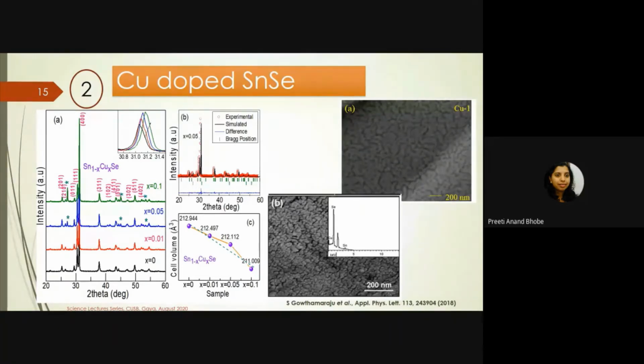But the amazing thing that we see is the change in microstructure. The right topmost corner figure shows you the microstructure for a 1% doped copper. And the moment you go to 8% copper, the microstructure has changed completely. And mind you, the magnification scale is the same, 200 nanometer scale. And you see a complete change in microstructure. This drastic effect surprised us, and we wondered whether this really plays a role in SnSe.